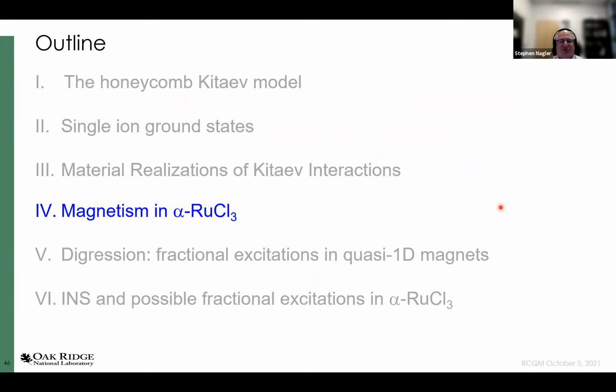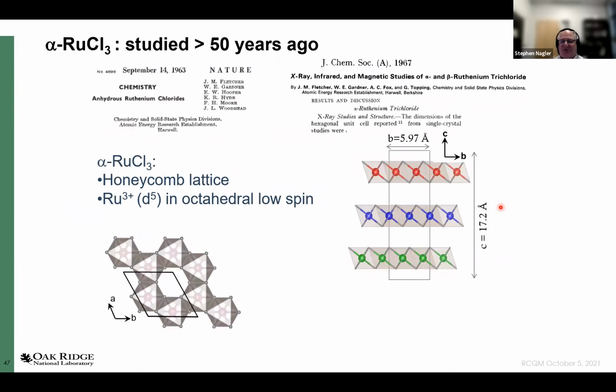So let me now turn specifically to alpha ruthenium trichloride. This is a material that's been studied for a very long time. I draw your attention here to a couple of papers from 1963 and 1967, where people looked at its structure and the magnetism. And alpha ruthenium trichloride indeed has a honeycomb lattice. It has ruthenium 3+, which is d5, in an octahedral surrounding in the low spin configuration. So it meets all of the criteria for a system to have Kitaev interactions that I mentioned before.